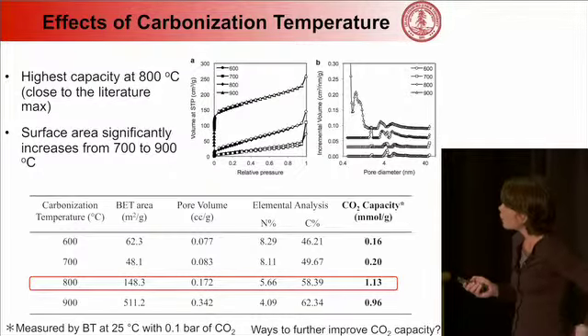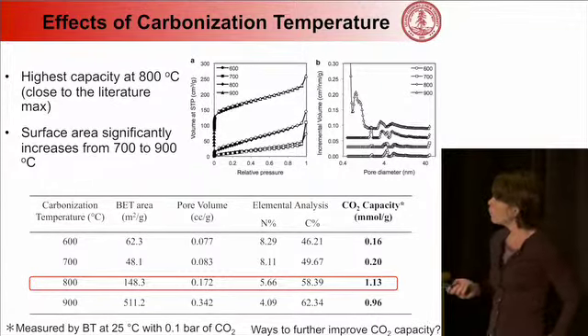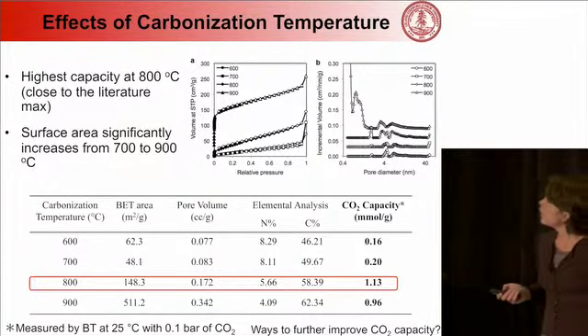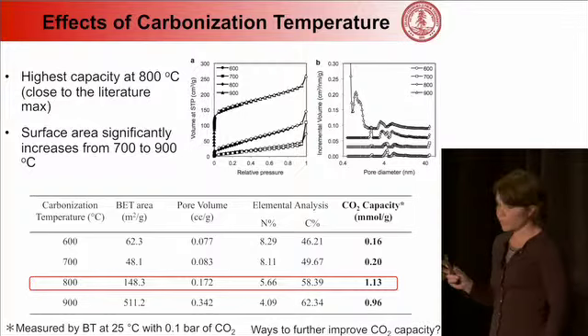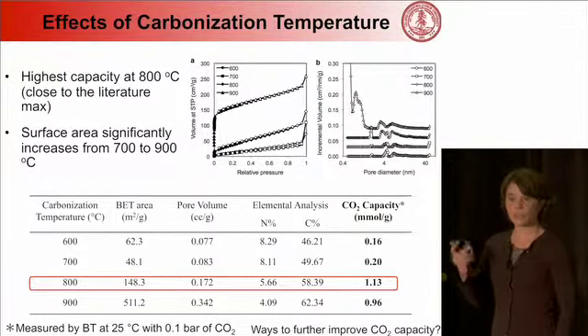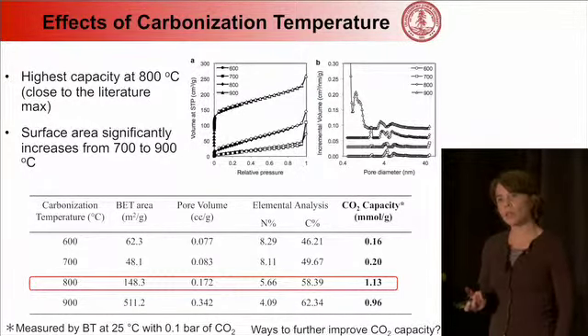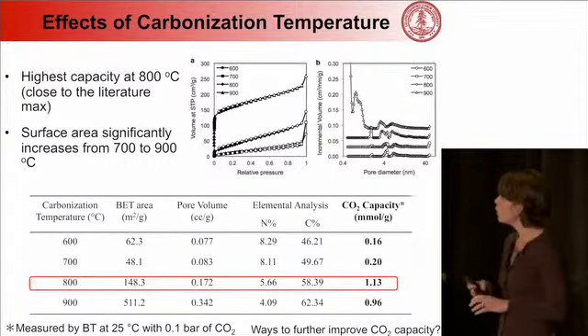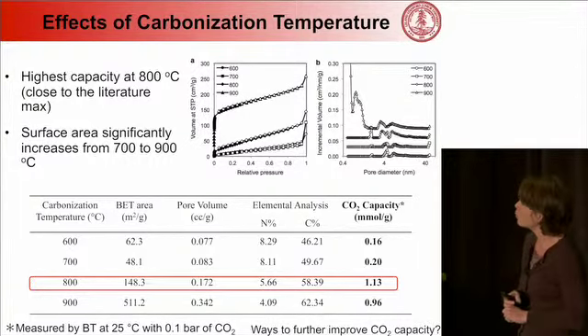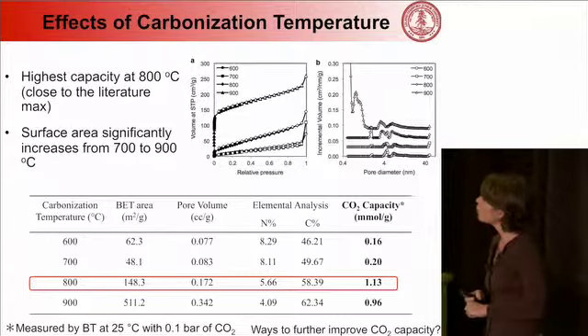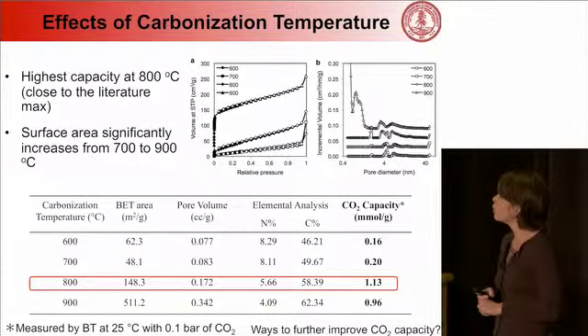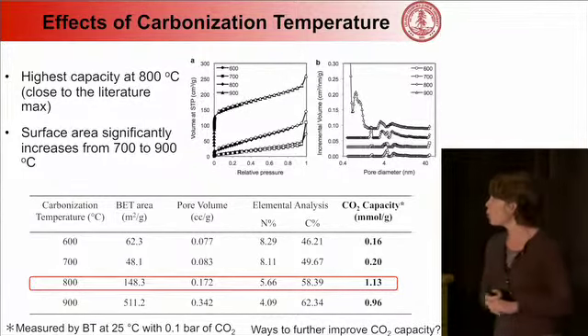So to look at that and compare it to the work that we've done so far, there are different sensitivity parameters. So for instance, nitrogen loading on the polymers, the carbonization temperature, and the method by which we actually functionalize the material so that we can control the pore size distribution. So this is the effective carbonization temperature here. And in the plots up on the right, the first one is just looking at the adsorption capacity of our materials as a function of carbonization temperature with respect to the relative pressure. And then the diagram on the right is the pore diameter.